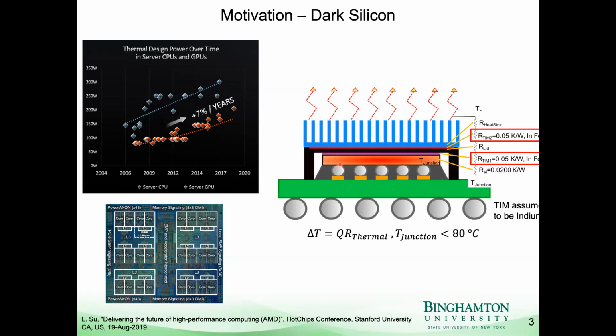Before it gets to that heat sink, it has to pass a number of layers. And one of the first layers it has to pass is called a thermal interface material. So if you have a 1 centimeter squared chip, your approximate thermal interface material resistance is going to be 0.05 Kelvin per watt. So if your chip is outputting 100 watts, like it was maybe 5 years ago as an average heat flux, your temperature difference across the thermal interface material would just be approximately 5 degrees Celsius.